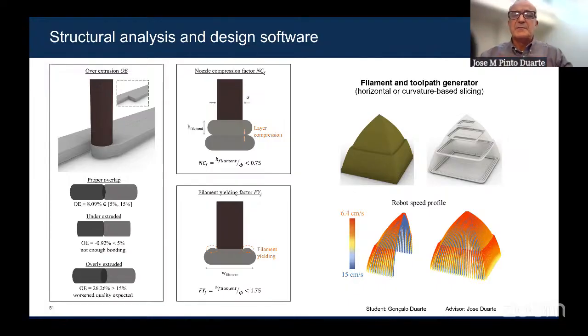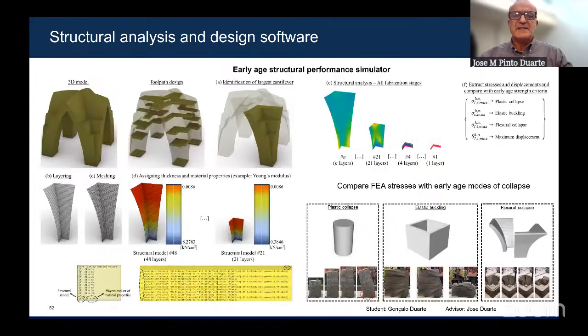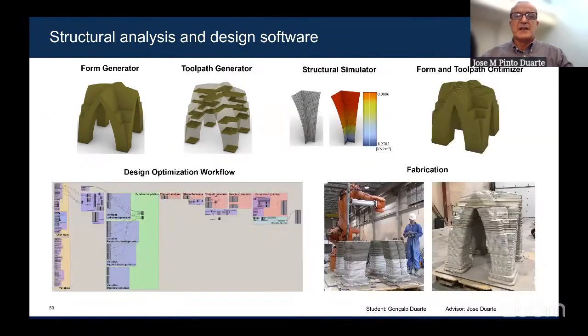So you need a filament predictor to understand the shape of the filament. And then you need to simulate the structural performance of the material, taking into account that different layers are at different stages of hardness, and therefore have a different level of strength. And then you can do the simulation, the finite element analysis, taking into account these differences in the material properties. And then you develop the tool path generator.